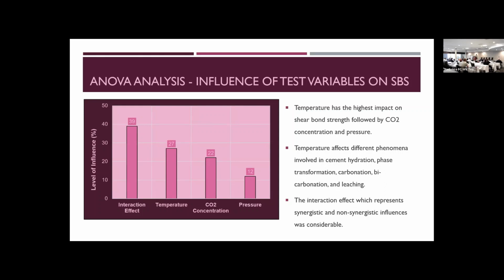complex question we have in most of the cements, and that's why we believe that almost every cement we put in a well needs to be first tested for interfacial shear bonding strength in order to make a case whether it will develop better bonding at elevated temperature or lower bonding. And if you remember, most of my tests with pure neat cement have shown a decrease of shear bonding at elevated temperature, whereas some of the tests here showed a trend of increasing with the temperature increase.